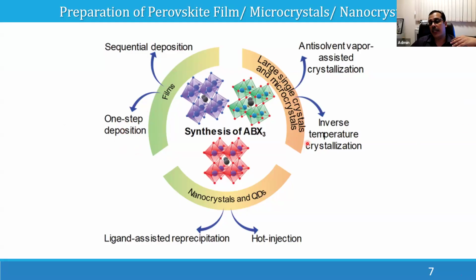And in some cases, we go for large single crystals or microcrystals. For example, for photo detector applications, it is better to have crystals in some cases. And in many cases, for sensor applications or even detection of X-rays, crystals are better. You can make crystals of this material very easily, like with a simple anti-solvent vapor-assisted crystallization.